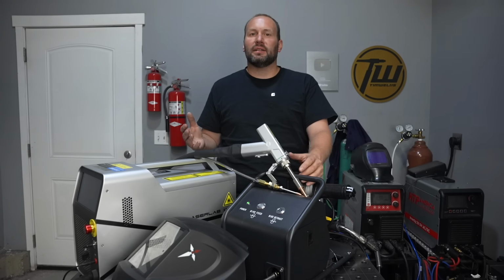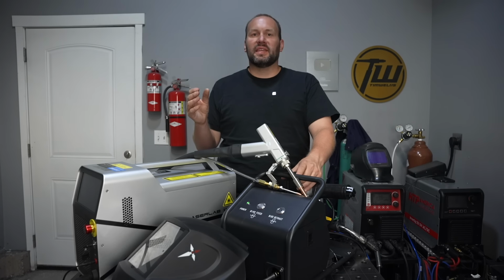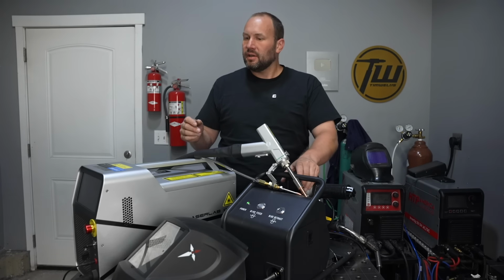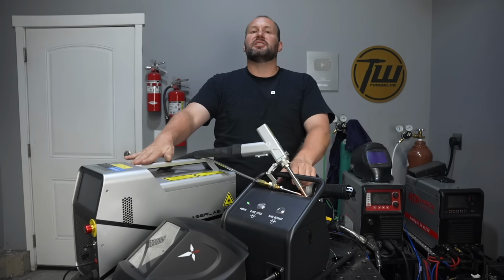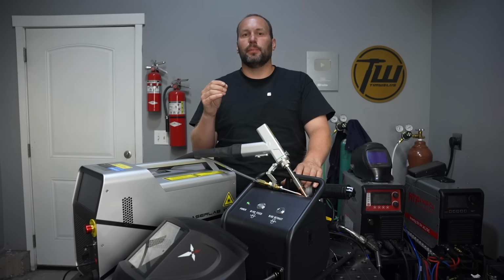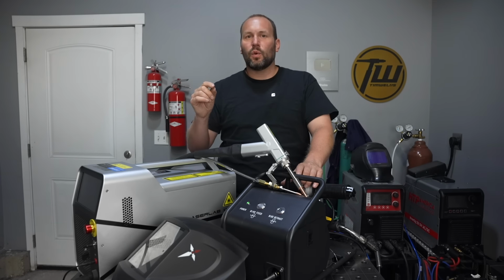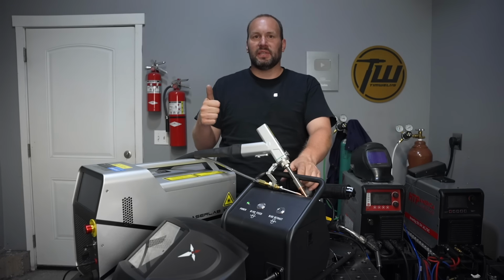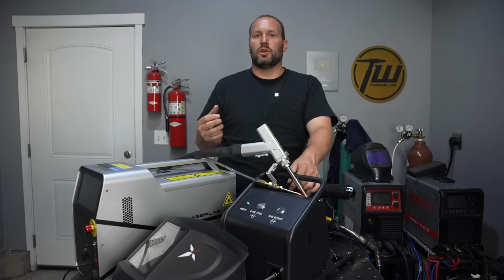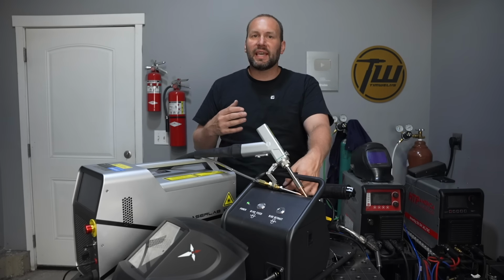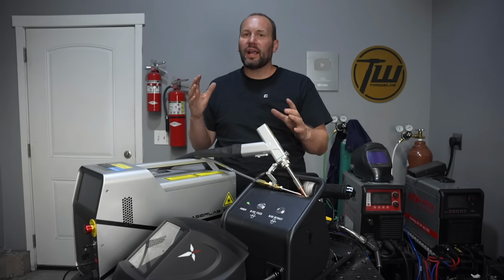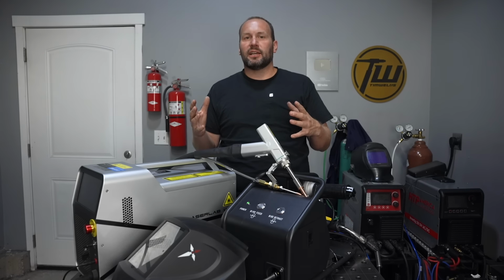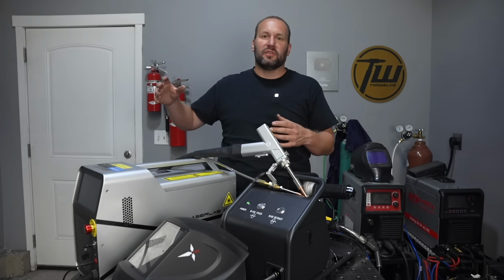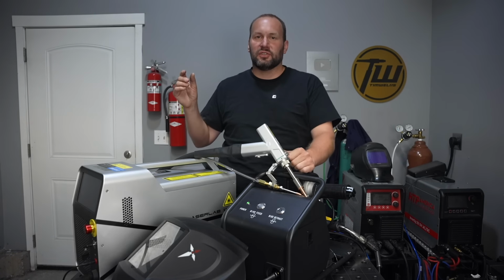When it comes to welding mild steel, for that 1/8 inch or 3mm thick and under, this laser weld has a ton of advantages, particularly when aesthetics are important, because that tiny little weld with no cleanup on a railing or something like that, just gonna be money. Also on sheet metal work, things like that. Now, as you get to thicker materials, the wire feed processes really take over. MIG, and even you get into dual shield flux core and maybe some spray transfer if it's real thick.